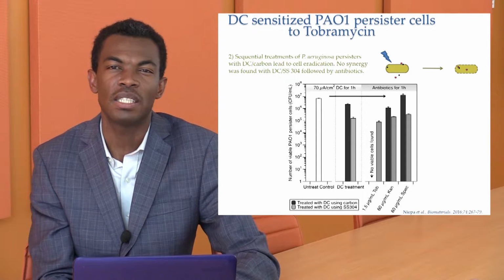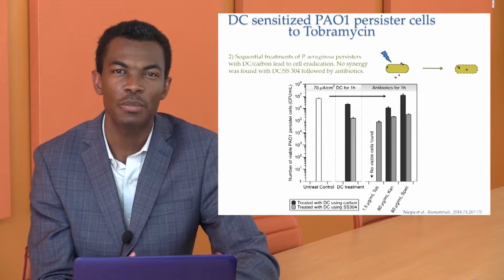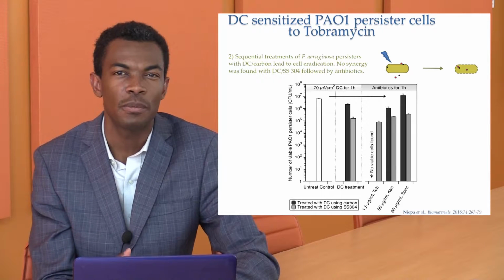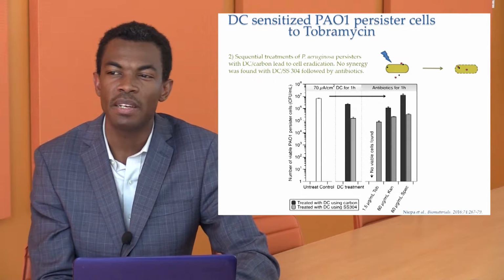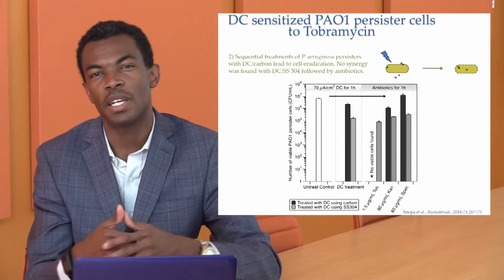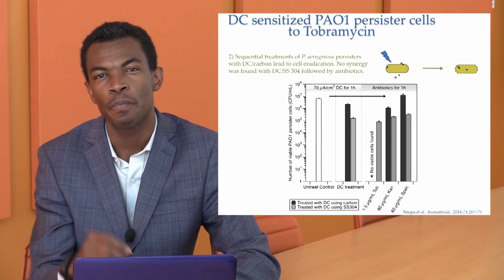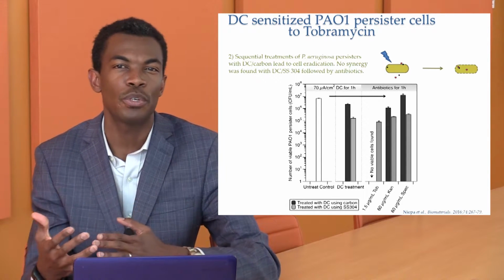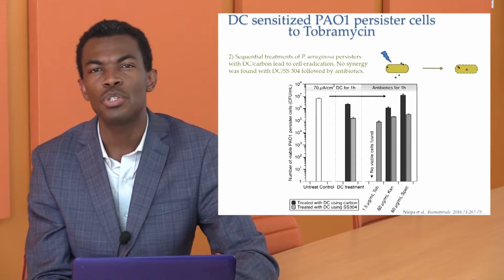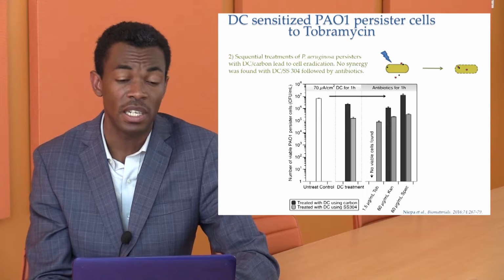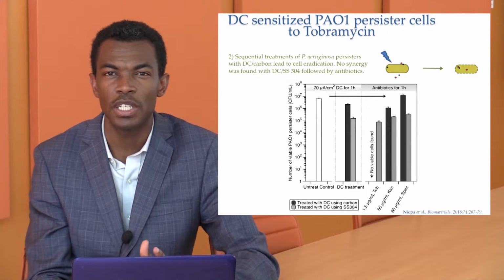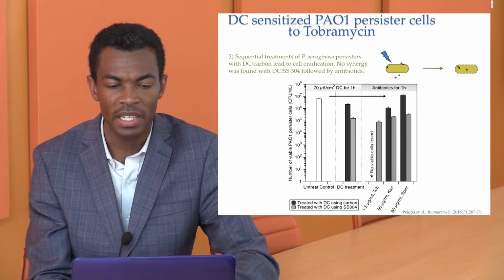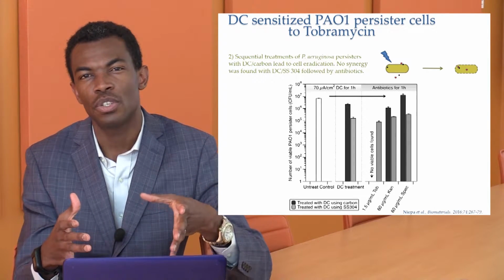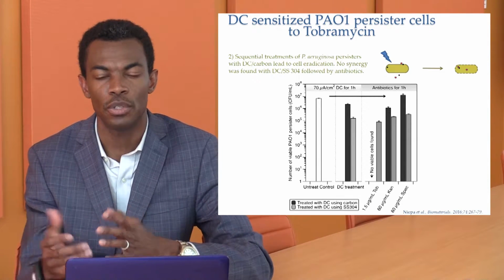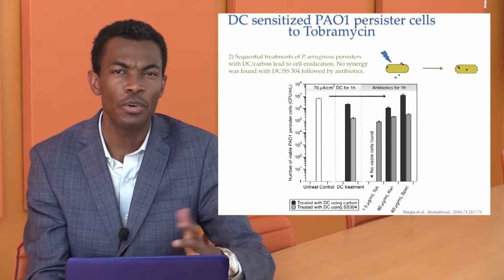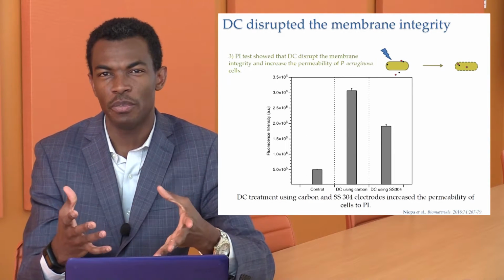By giving such an amount of drug to the cells treated with carbon electrode, we wipe them out completely. We eradicate all the cells, we kill them. Meaning that maybe the current generated by carbon electrode is a means to create some pores in the cells or activate them so that something that was not killing them finally killed them. But we were not able to achieve the same condition with other material, even stainless steel, which we think was very intriguing because stainless steel was very performant. But at least it told us something, that the DC treatment somehow permeates the cells so that toxic material can enter, confirming our hypothesis.